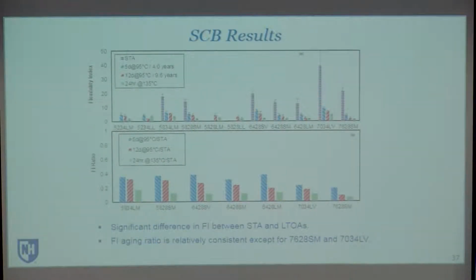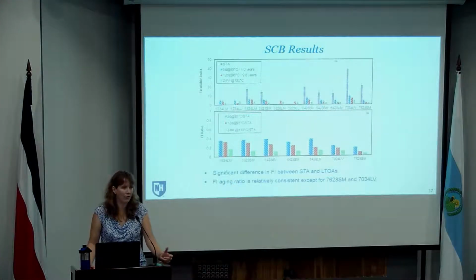Moving on to the semicircular bend test results. Same type of figures here with the flexibility index values that we're showing in the top figure. So these are the actual values from the test results, and you can see those polymer modified mixtures have huge FI values. If any of you have looked at SCB results, typically any flexibility index value 10 or above is considered pretty good, and we're looking at numbers that are up around 40 for these mixtures in the short-term age condition.